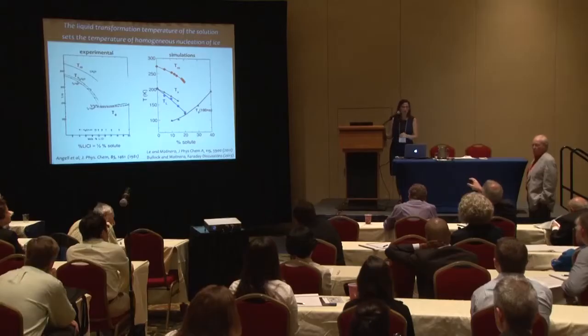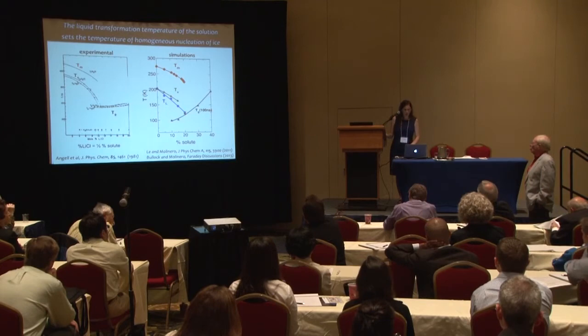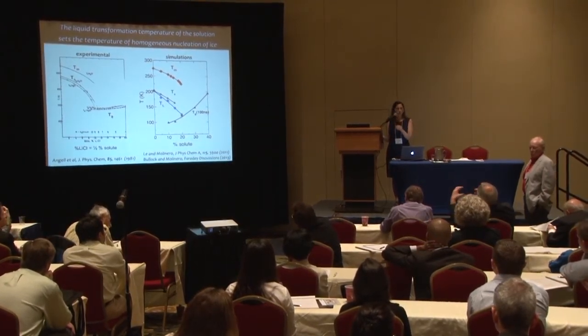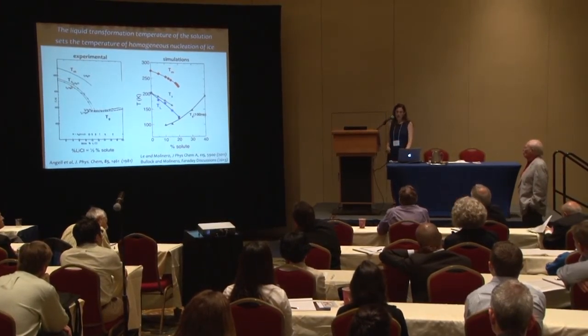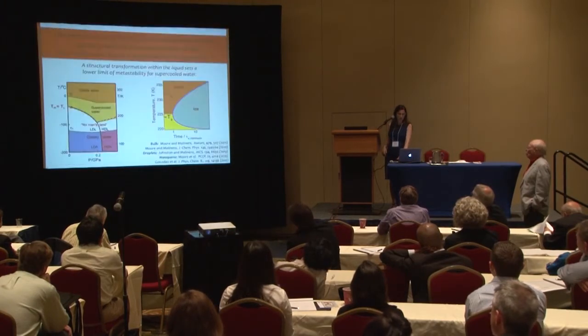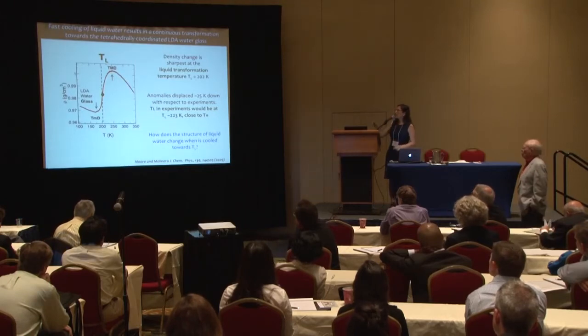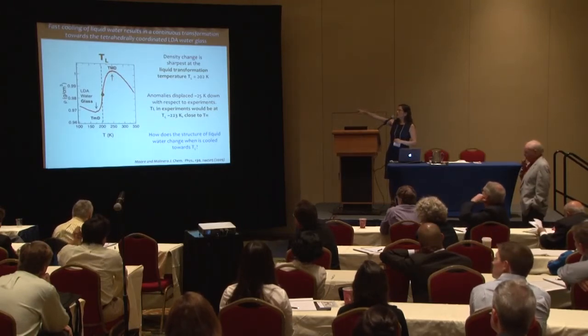These micro-domains are all fluctuations within the same thermodynamic state. The density falls as we go from the temperature of maximum density to the green point — the density of the liquid falls in experiments to about 0.93. The more blue (four-coordinated, lower density) you have, the lower the density. This explains the decrease in density of liquid water. As the blue domains also have lower enthalpy, and the more cooperatively they form the faster enthalpy goes down, the heat capacity — the derivative of enthalpy with temperature — increases.